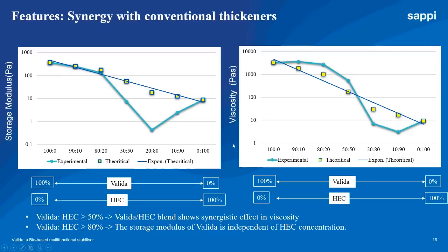First of all, on the left side of the slide, the storage modulus of Valida and HEC is shown. We can see 100% of Valida in formulation and 0% of HEC. So basically the storage modulus of Valida is almost 2 orders of magnitude higher than that of HEC. And this also explains the much higher stabilization feature of Valida compared to HEC. Then we see that when we have in the formulation a ratio of 80 to 20 Valida to HEC, the storage modulus is not affected by HEC. On the right side we have a viscosity graph.